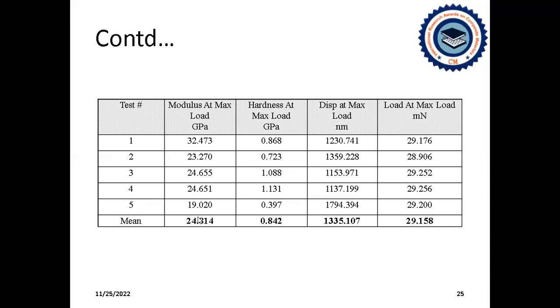We found the low Young's modulus, which is favorable for biomedical implants, since low modulus titanium alloys will benefit as an implant material for biomedical applications. If it is a high modulus, then it will end up with the stress shielding effect. So low modulus titanium alloys are preferred for implant materials in biomedical applications.